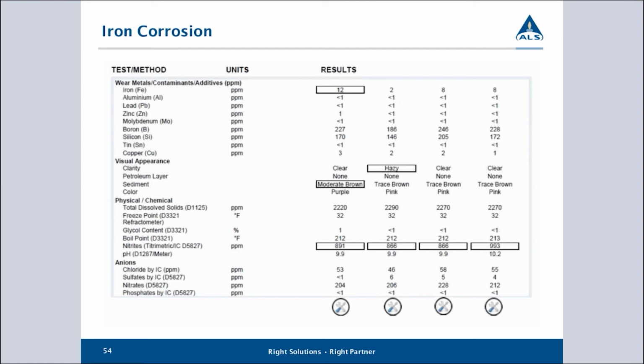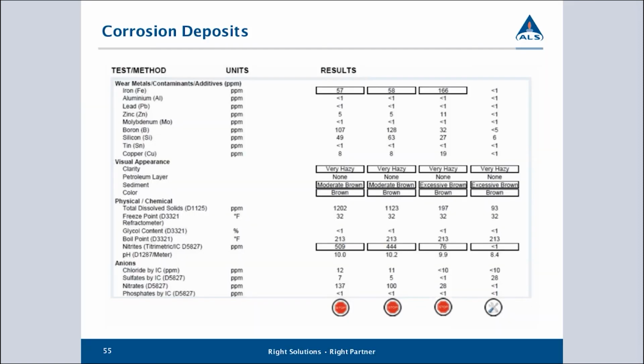And we need higher levels of additives to try and stop corrosion in the system. So again, what we should be doing here is, because we're seeing active corrosion, we need to flush this material out and then refill with a new coolant, and then just monitor it closely to see, is the corrosion dropping off or is it accelerating? If it's accelerating, we might want to dig further and see, do we have high temperatures or something that is driving the corrosion we're seeing in this particular sample.